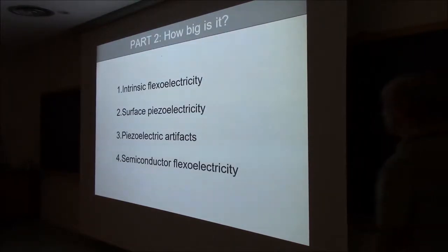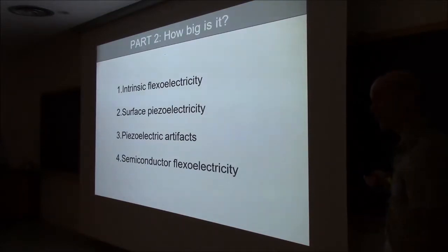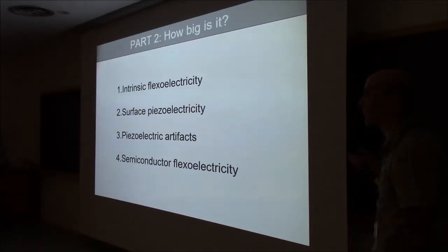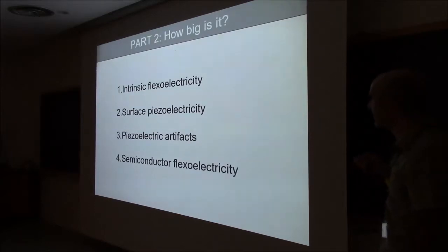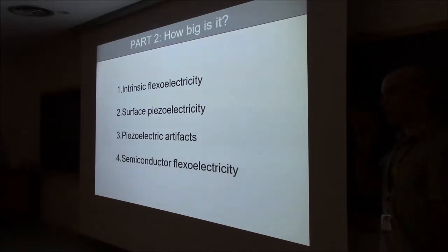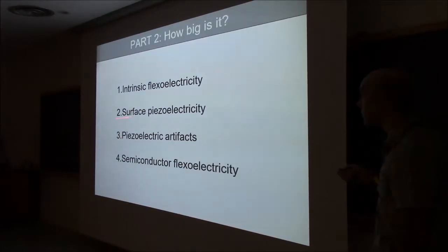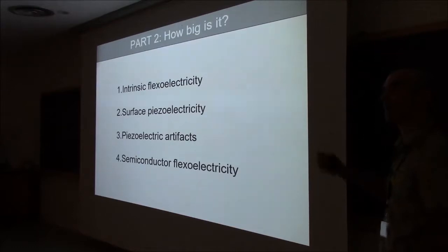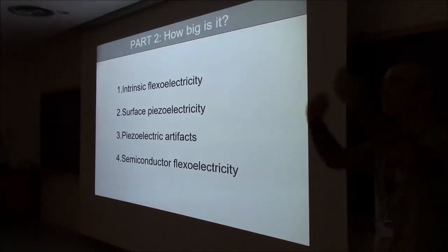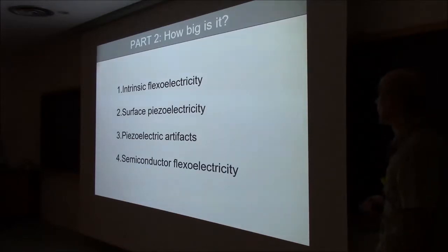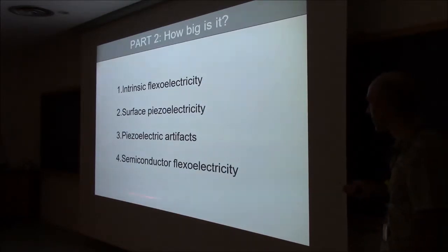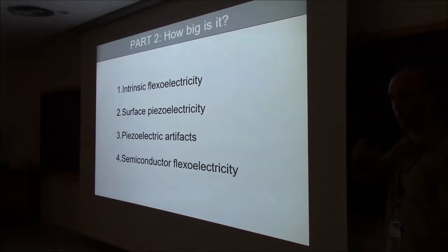Okay, so how big is flexoelectricity? This question is not trivial, and I dedicated quite a few years of my life to trying to answer it, because flexoelectricity has an intrinsic contribution, but on top of this intrinsic contribution, there's another contribution which is surface piezoelectricity, which is not exactly intrinsic, but it's always there. So in a sense, it's inherent. You can never get rid of surface piezoelectricity. You can also have piezoelectric artifacts if your material has polar nanoregions, or has a gradient of defects or whatever. And finally, if your material is a semiconductor, you can also have some free charge contributions. And all of those can change enormously your flexoelectric coefficient.